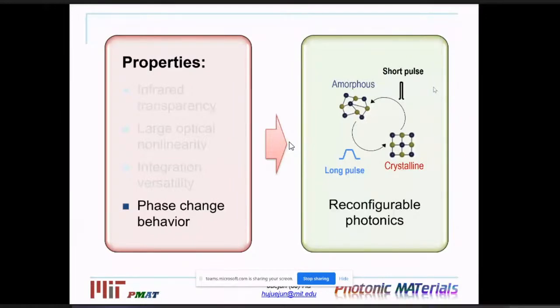One is the temperature you go up to. The other is essentially the trailing edge, or how fast you quench down. So if you want to amorphize it, you have to go above the melting point. So this dictates the voltage you have to apply. In our case, depending on the material, if it's GSST on the doped silicon, we can go as low as about 5 volts to amorphize it.